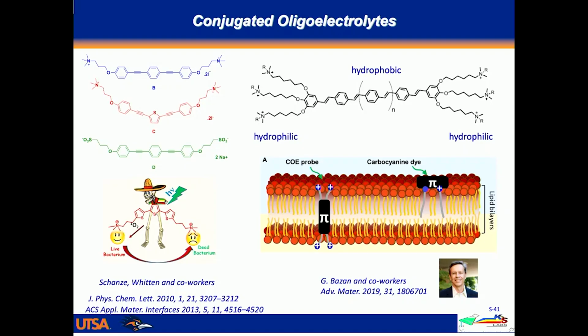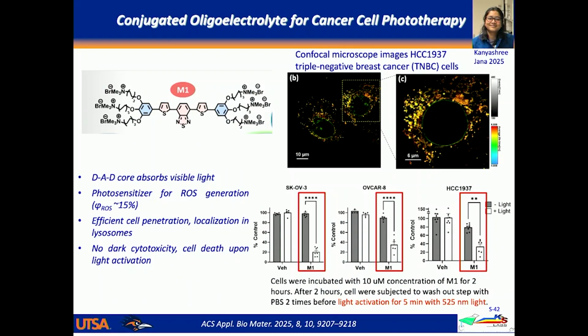And so we became interested in this idea, but bringing it together with the donor-acceptor-donor type of structures that are used in polymers that are used in optoelectronic applications. So this graduate student, Kanyashree Jana, made this molecule. It's a polyelectrolyte that contains this thiophene benzothiadiazole donor-acceptor-donor structure with these 6 positively charged groups on it, making it very membrane active. If you add this polymer to mammalian cells, the mammalian cells very rapidly take it up. These are images taken of a breast cancer cell line called HCC 1937. Most of the molecule is in lysosomes, but you can see a green sort of stripe around in this region. I'm trying to point at it. That's the nuclear membrane.